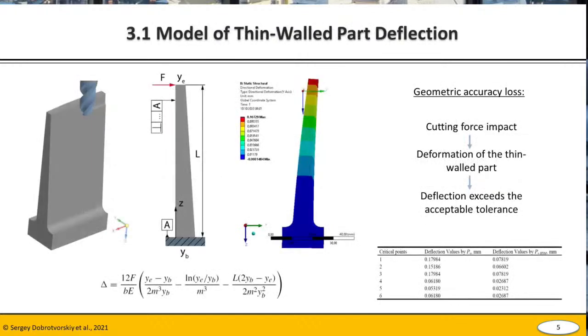In the process of thin-walled part manufacturing, undesirable deflections occur in the direction of force impact, and this leads to non-compliance with requirements, as the deflection values exceed the acceptable tolerance zone. We investigated deflections for the most critical points, for conventional machining and for high-speed milling, and the model of the deflection is formulated including geometry parameters, generalized force, and the measure of material stiffness.